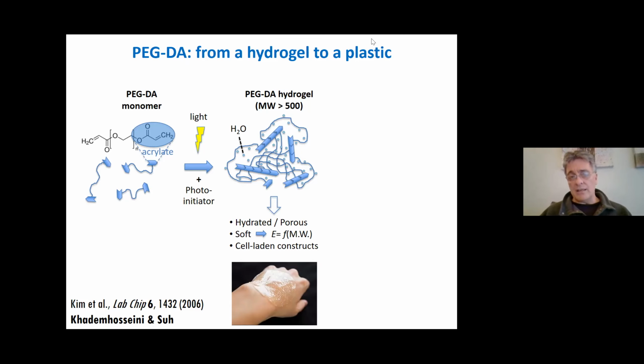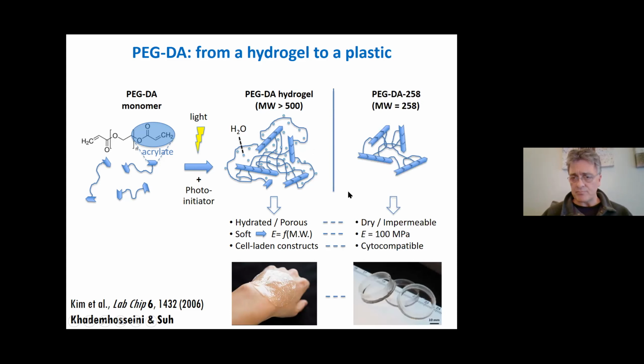There are already very nice materials, most notably PEGDA, polyethylene glycol diacrylate, which has two acrylate groups at the ends. Based on the molecular weight of the monomers, when you add the photoinitiator, you can get either a hydrogel, if you have a large molecular weight that associates with water during the polymerization process, or, if you have a low molecular weight compound like PEGDA 258, essentially a plastic.